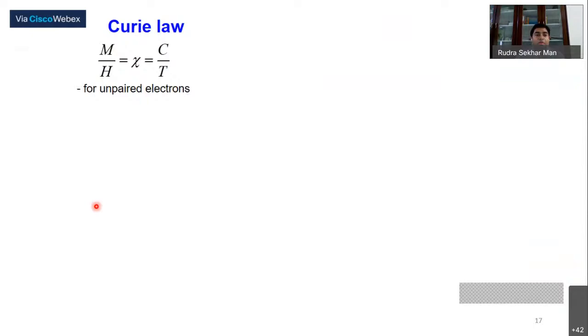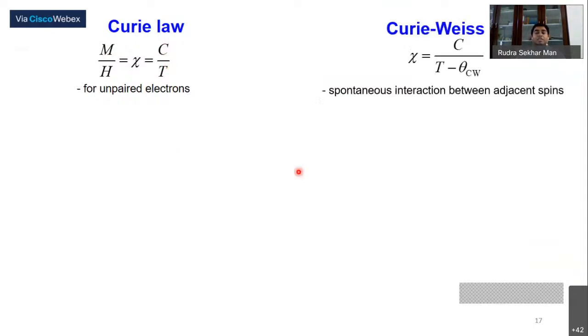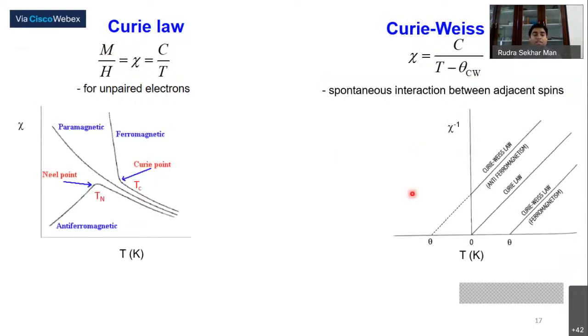For unpaired electrons, you apply a magnetic field and then you calculate the susceptibility, which is nothing but a 1 over T type of dependence. If the electrons interact with each other, with some kind of interaction between adjacent spins, then the Curie law develops into the Curie-Weiss law. One can then see typical examples of the magnetic susceptibility for different phases: paramagnet, ferromagnet, or antiferromagnet. A paramagnet is simply a 1 over T type of behavior, and that can be easily seen in the right-hand side plot, because if you plot 1 over chi, that is chi inverse, you get simply a linear dependence on temperature.